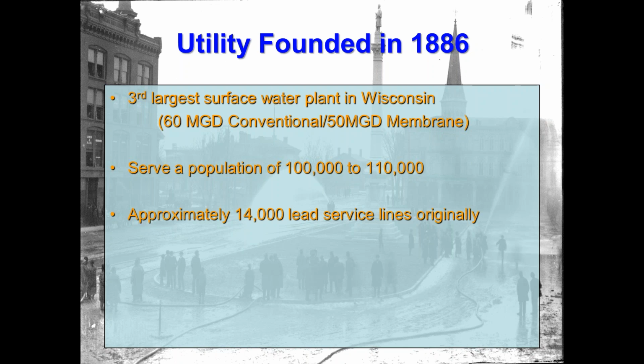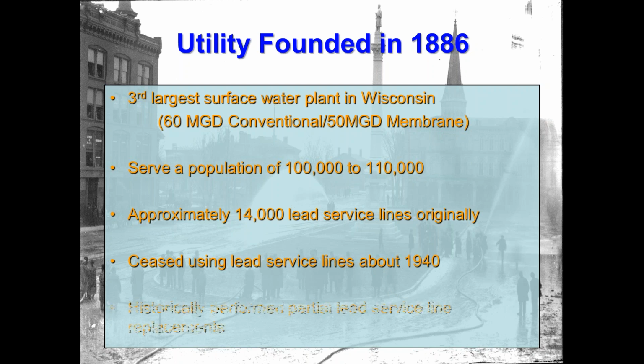We started out with approximately 14,000 lead service lines, probably about 2,000 to 3,000 less than that right now. We stopped using lead service lines in around 1940, right before World War II. And historically, we've been performing partial lead service line replacements as we do water main projects. Again, that's kind of a no-no. Obviously, now with what's done in research and the potential for elevated lead levels, we've received some grant money the last couple of years from the Wisconsin Department of Natural Resources to help our private citizens replace their side of the lead service line, and we're progressing with that quite well. So where we can, we do full lead line service replacement.